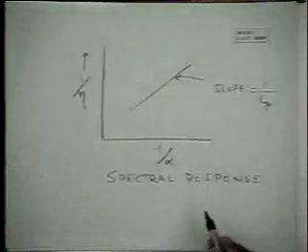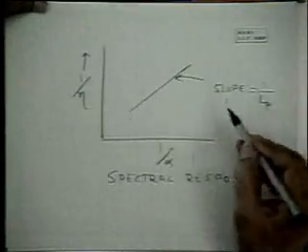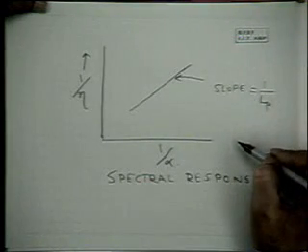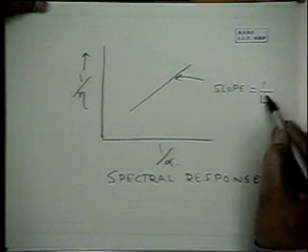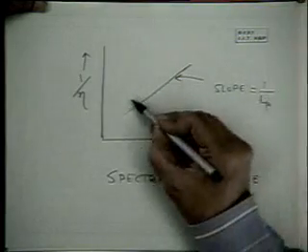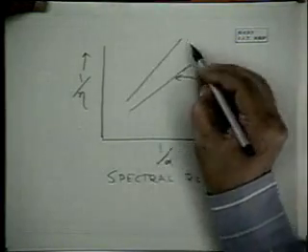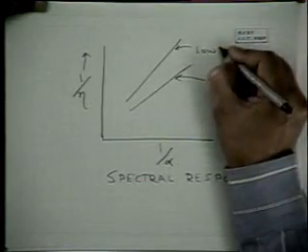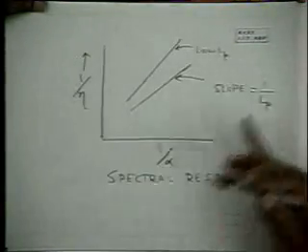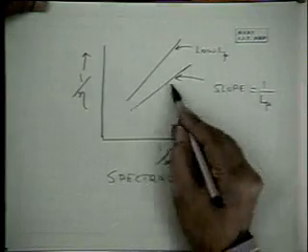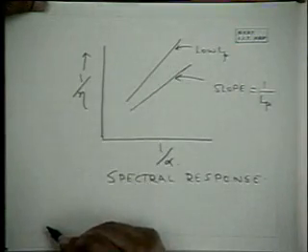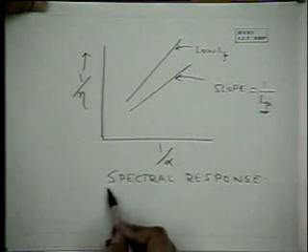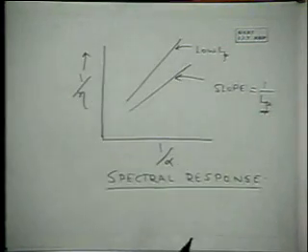So, for example, if LP is small, we will get a variation like that. And if, for example, the surface is passivated, then we'll get a variation like that. So this is a standard method of determining LP from the spectral response of a solar cell.